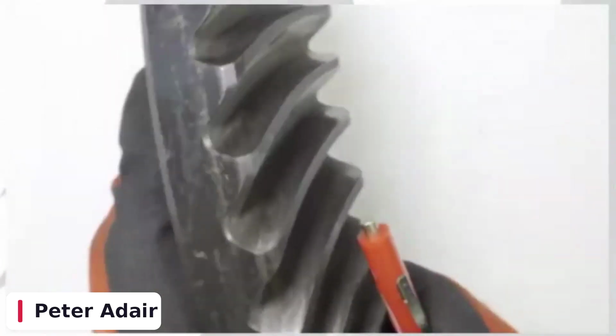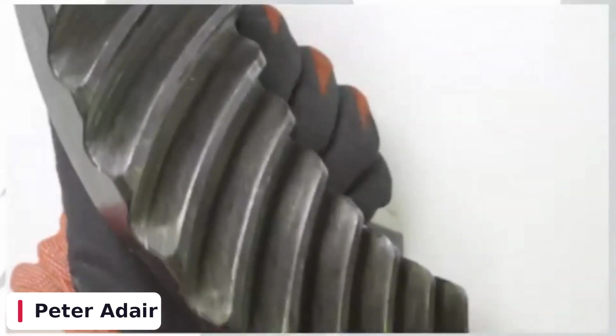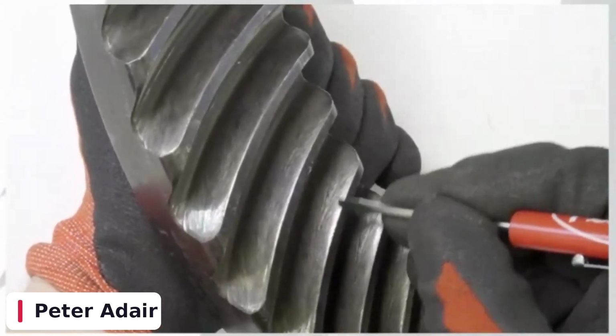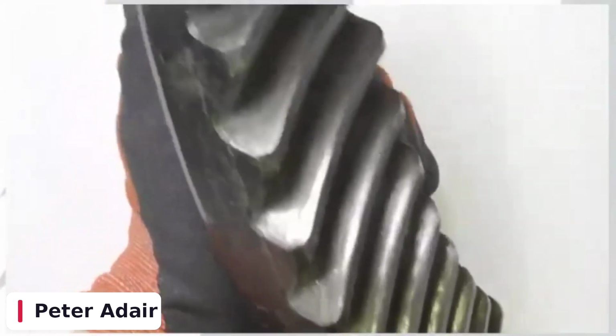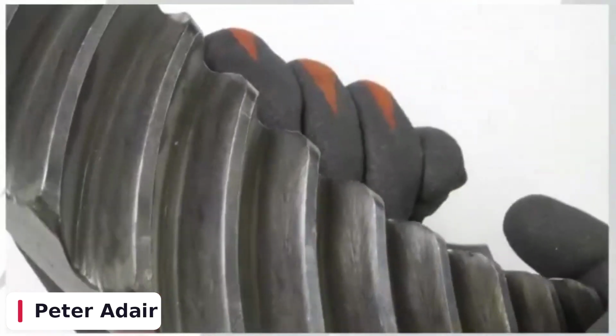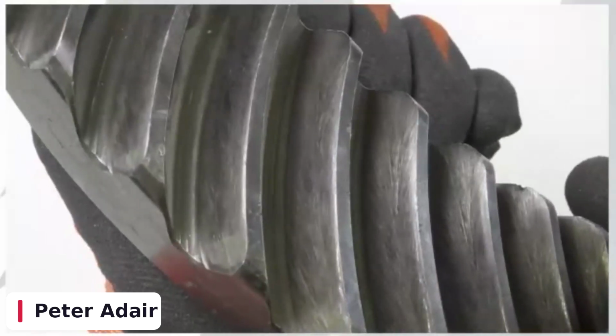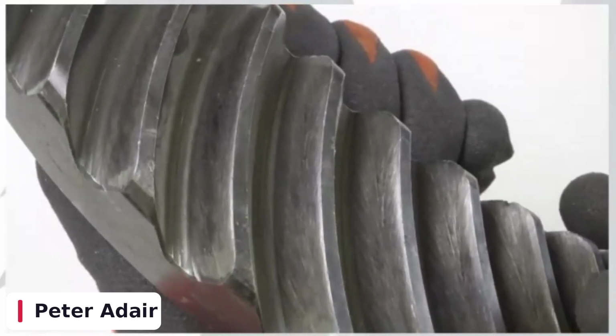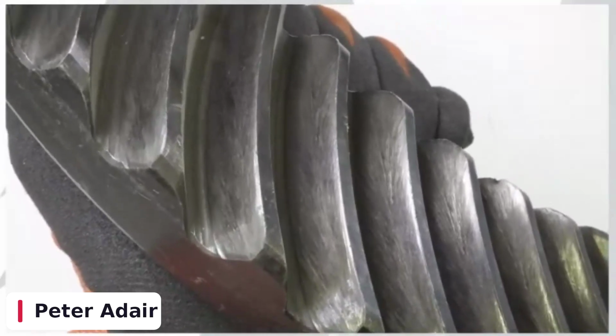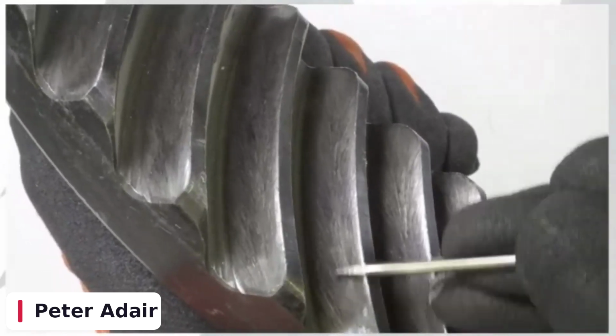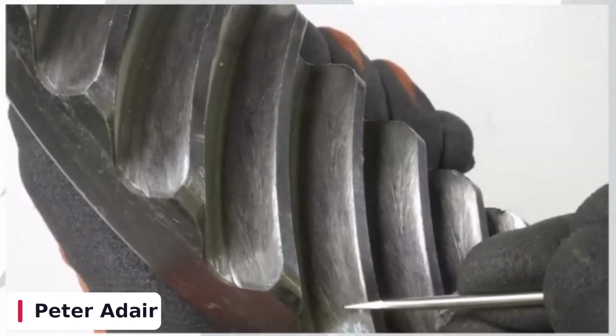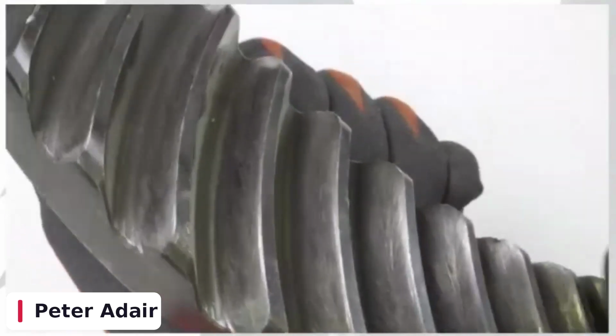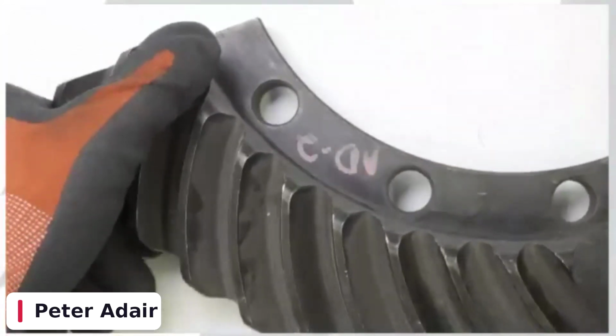So when we're looking at an example like this, axle oil is supposed to have a certain additive package. The main additive package we are looking for as Cummins Meritor is GL5 or an EP additive. If you lack the GL5 or the EP additive, you're going to get what we call crow's footing, which is what this is.